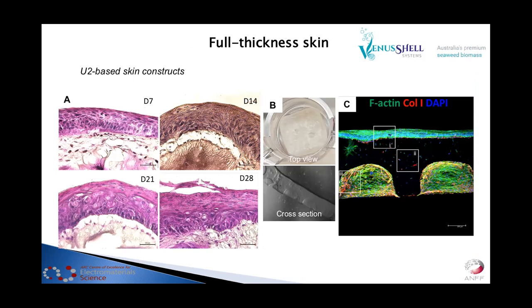Then a full-thickness skin model was constructed by culturing HaCaT keratinocytes on top of the 3D printed dermal-like structures based on bioink U2. The HaCaT cells were allowed to differentiate at the air-liquid interface for up to 28 days. Histology studies showed that HaCaT cells successfully stratified, as evidenced by the increase in the thickness of the epidermal layer and the distinct orientation of the cell nuclei.